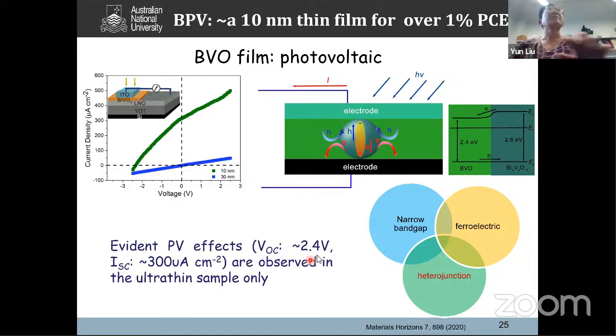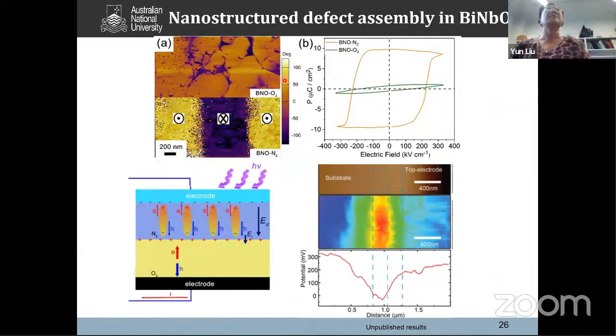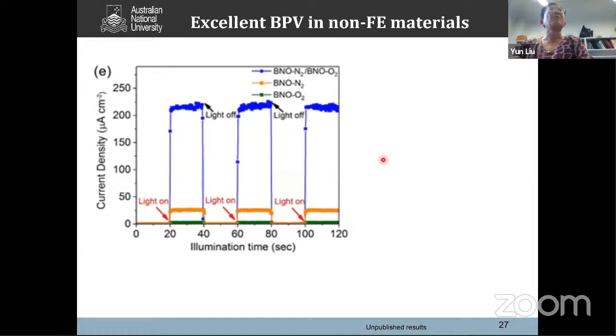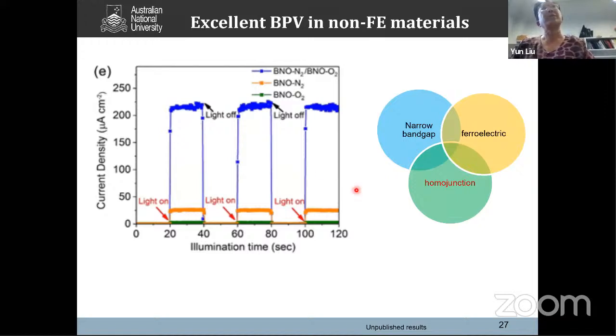Okay. Similar things we also do for bismuth niobium oxide. In that case, we can introduce a defect, and then we make these materials become ferroelectric and non-ferroelectric, and we pack them together to form an interface junction. And as a result, again, here we form homojunctions, and then we can enhance the bulk photovoltaic effects. Okay, so that's a few examples indicating how we can change the local structure environment to make unique materials, which can combine different strengths together, and remove the weakness of one of them, and then make materials more useful.